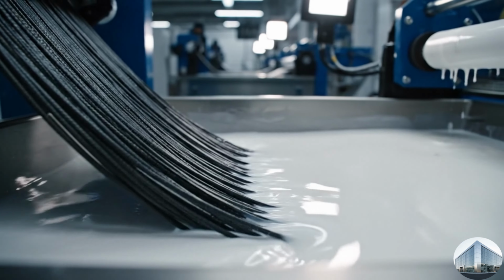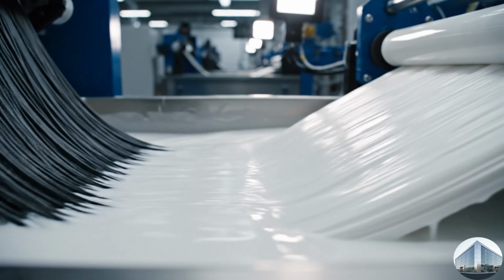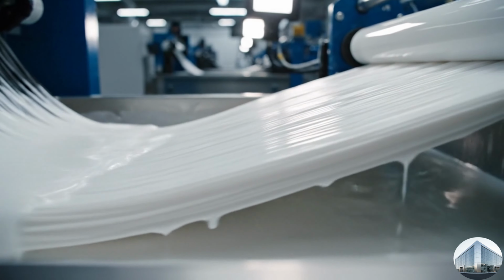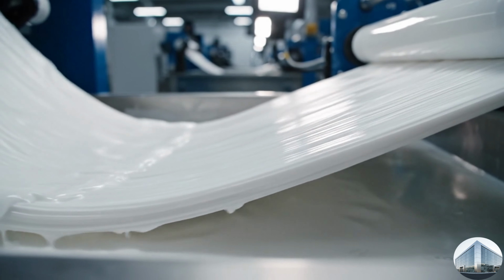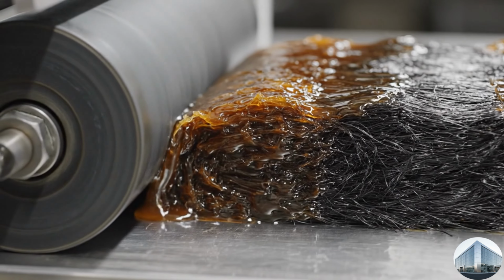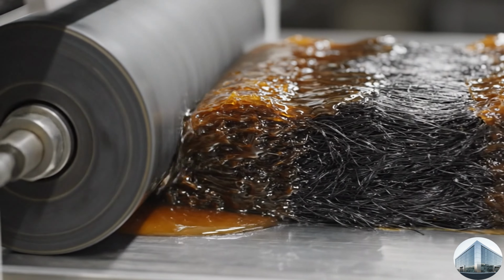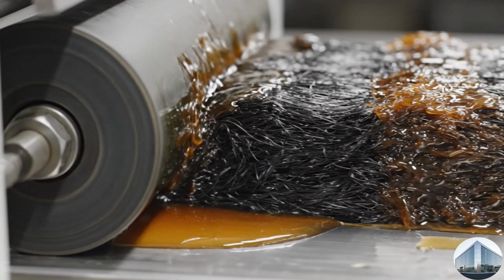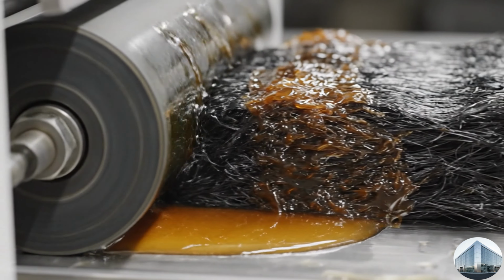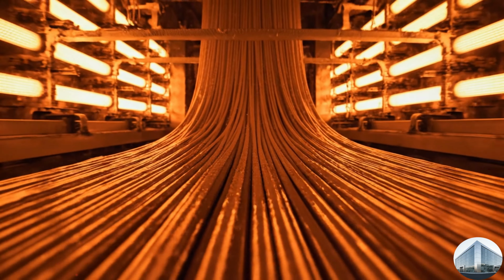Strength alone is not enough. The fiber must be able to bond. Surface treatment through electrolysis creates microscopic roughness, allowing the fiber to grip the resin in later stages. A protective coating, called sizing, is applied next. This thin layer of resin protects the delicate fibers from damage during the weaving process and improves chemical compatibility.